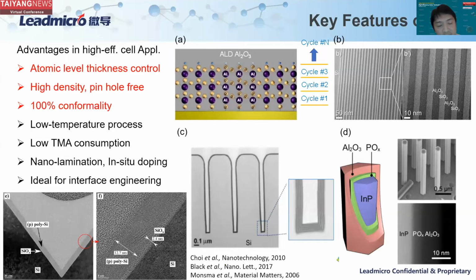If you look at the bottom left corner, the TEM and SEM images, you will see that unlike the PERC cell, where we passivate the rear side, the poly surface, in TOPCon cells you need to passivate the front surface. We all know that the light receiving side needs a textured surface. If you have to passivate the textured surface, conformity becomes a challenge. ALD has the advantage, and that's the main reason it has become a standard technology.